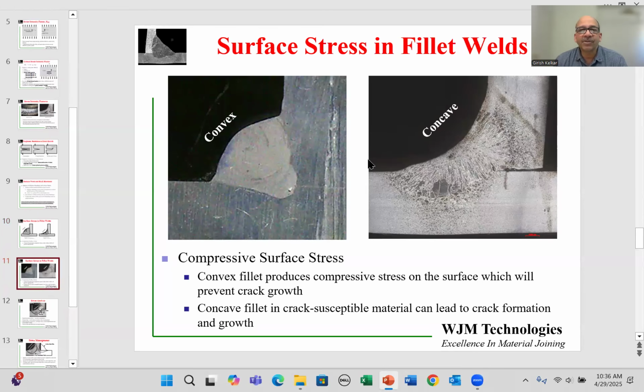Let's look at the different profiles. On the left is a fillet weld with a convex profile. This profile on cooling will have compressive stresses on the surface, which will help to close the cracks. Now, these compressive stresses are a reasonable amount, so they're not purely on the surface. They would probably go more than half into the bulk as well. On the right, I'm showing you a concave profile. A concave profile will introduce tensile stress on the surface. And if there's a crack, then it is more likely to grow in that weld.